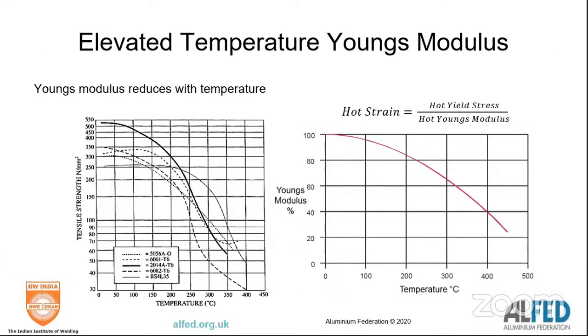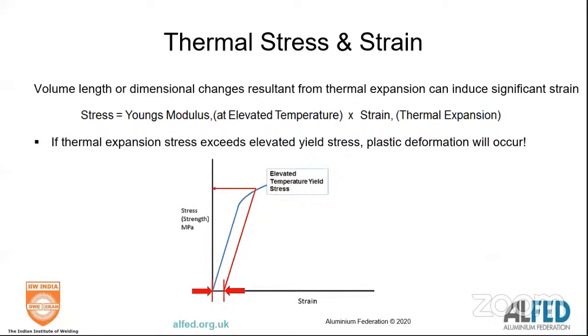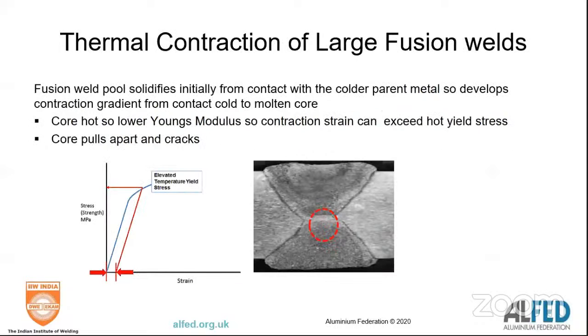But Young's modulus falls off equivalently. So you see a big drop off with Young's modulus. You see a loss of strength, but Young's modulus falls off. So now aluminium at high temperatures has a totally different strain rate to that of room temperature. You now need to understand that you're dealing with a soft or weak metal with low Young's modulus, which is behaving very differently to room temperature. That has implications when you've got large fusion welds, because the outside of the weld can cool to room temperature, but in the middle you're still at high temperatures with a low Young's modulus and low strength, so you can pull them apart.